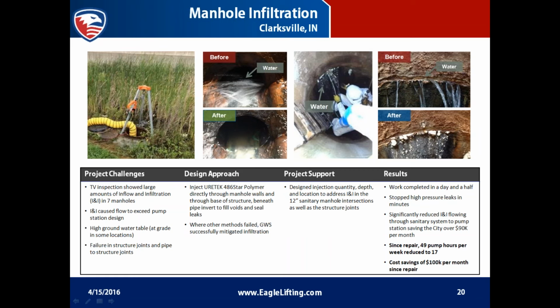This is a picture of a manhole that was done in Clarksville, Indiana. TV inspections showed large amounts of inflow and infiltration in 7 different manholes. Because of the hydro-insensitivity of the polymer, again, it makes a phenomenal leak sealant. So you can see where the faulted joints in the before and after picture had water infiltrating into each of the manholes. They had brick manholes, steel manholes, et cetera. And by performing the void filling operation specifically and deep injections also in order to densify the manholes and prevent further movement, they were able to effectively seal the manhole.